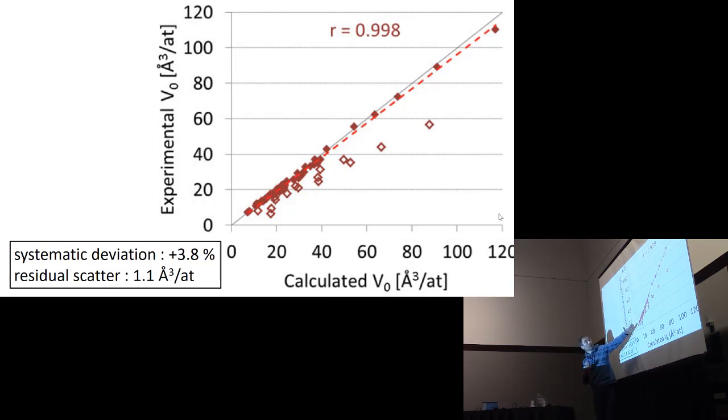There you can make a least square fit, which is this red dashed line. That shows you that there is a tendency for PBE to overestimate the equilibrium volume. If you want, you can correct for that. You can quantify that tendency. But even then, there is the remaining scatter of the data points around this linear line, the residual error on which you cannot help. So systematic deviation and residual error, these are the two numbers you get out of that plot.